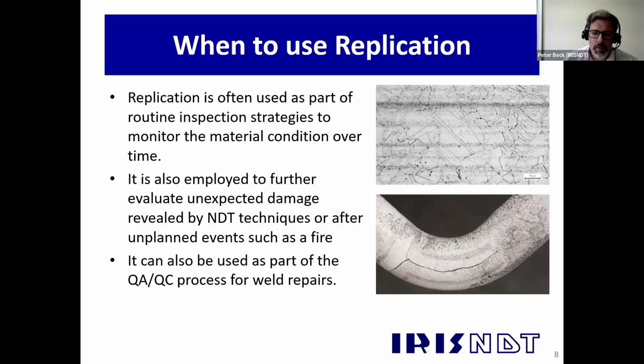We've also replicated on structural materials, structural steels after fire events. Obviously, fire can have a significant impact on the microstructure and degrade it and soften the material. So again, this is where I mentioned that we would also often do hardness testing. So for a fire, we might do replication and hardness testing to use as a double approach to assessment. Another thing that can be done is replicating any kind of welds or repairs in plant or even before it's been in service. So quite often with stainless steels, we might be interested in sigma phase or something like that that's formed. So that's where that kind of QA process would come in.